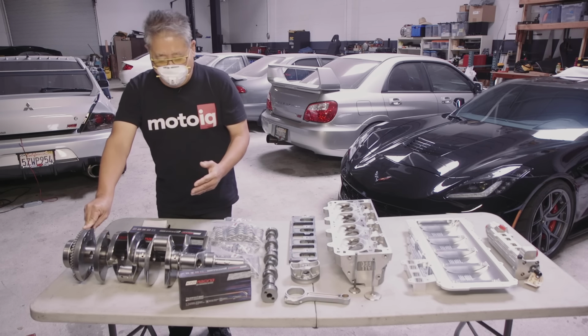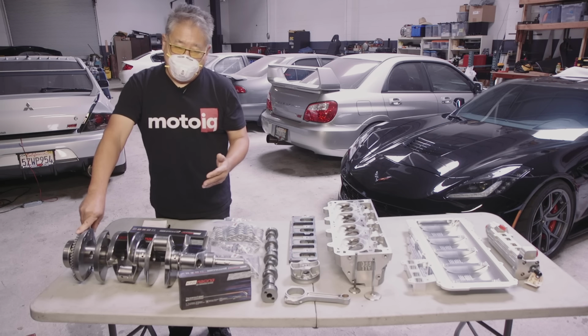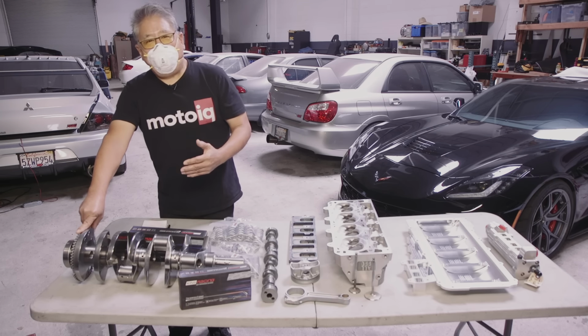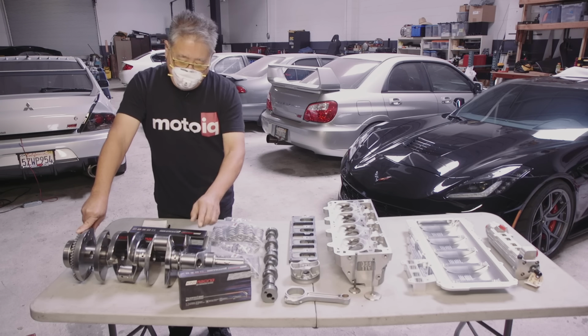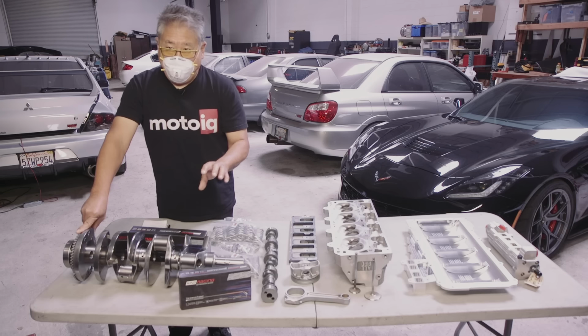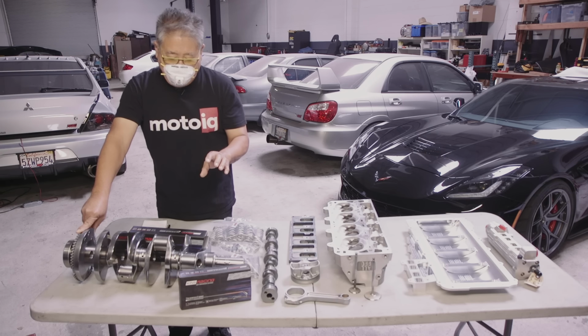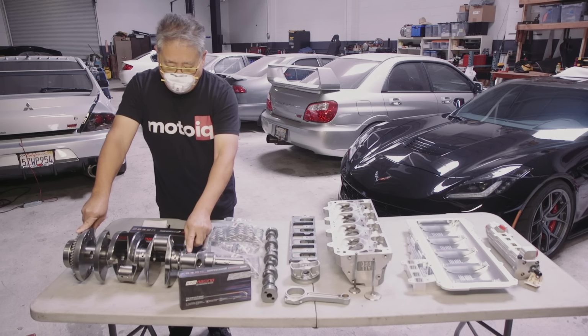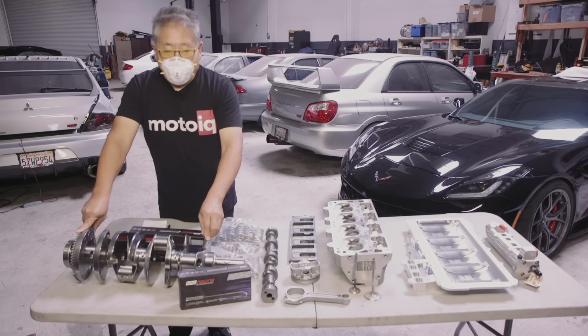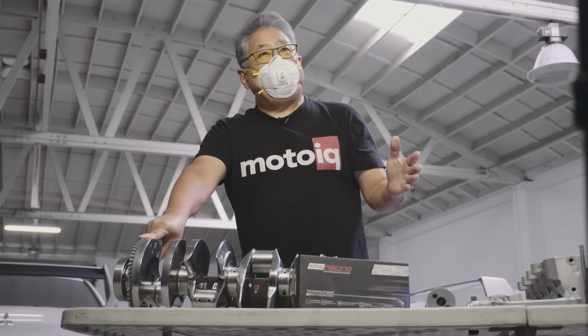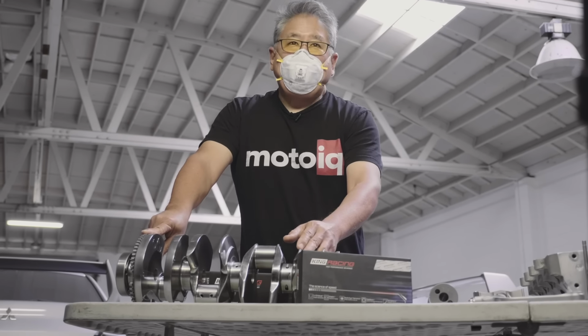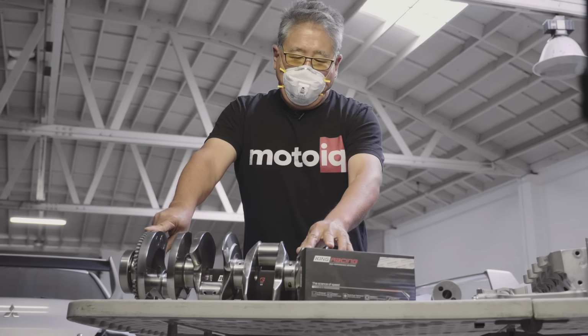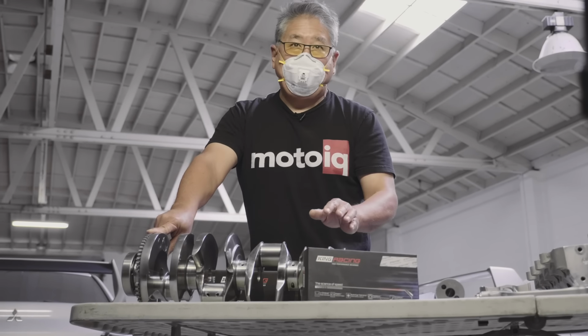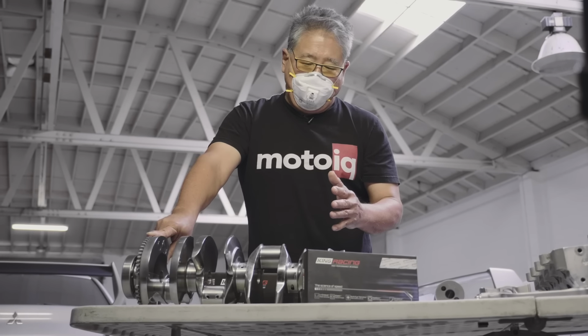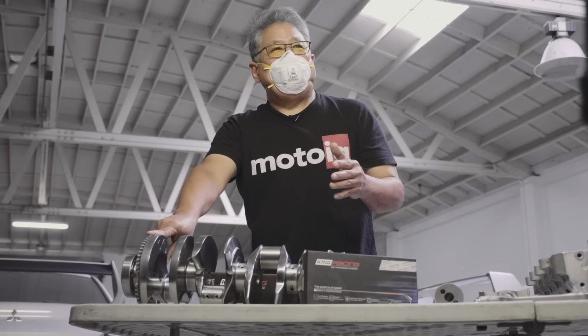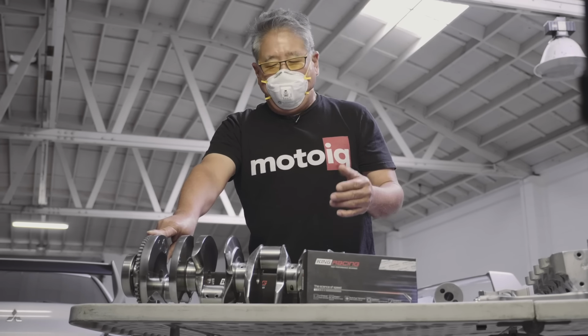Now, we talk about WPC a lot, but it's a Japanese super finishing process that's kind of like shot peening on a microscopic scale. It leaves a really fine compressed surface where it's hard for a crack to start. It really helps your fatigue strength, and it's ultra low friction. The Ra on the surface is lower than traditional super finishing, so it's a super smooth, super slick, really hard, thin surface finish that it's almost impossible for a crack to propagate in. So you reduce friction, you increase your life, and you increase your fatigue strength.